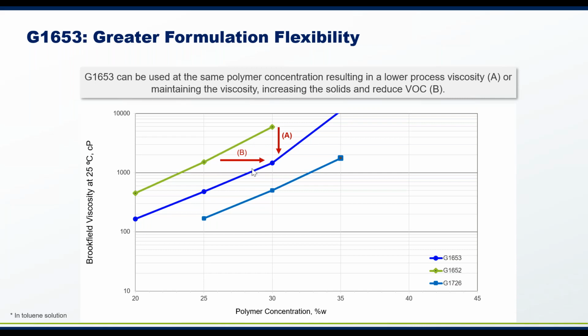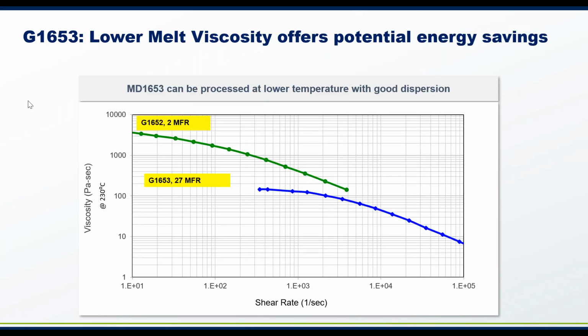The second knob, which was B in this graph, is maintaining similar viscosity, yet we increase the solids content from 25% with G1652 up to 30% by switching to G1653. Therefore, this could lower the amount of solvent used and result in less VOC in the coating. Here, we also have G1726 just used as a reference because it also has lower viscosity, but we realize that the strength and flexibility of G1726 does not equal that of G1652 or G1653.